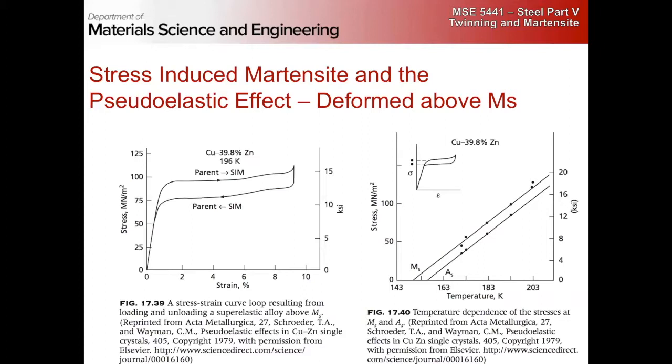It is reversible on the micro scale, right? There's anelasticity here, right? But on the very local scale, it's not completely reversible everywhere, right? And if you cycle this many times, the amount of recoverable strain decreases with the number of cycles, right?